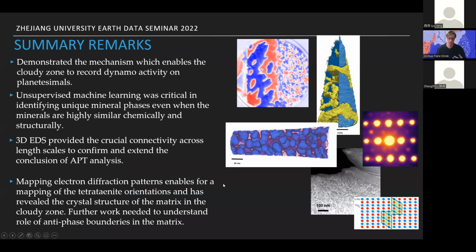The summary I'd like to point out is that we demonstrate a mechanism which enables us to explain why we're able to read magnetic records in the cloudy zone. Unsupervised machine learning was very critical in identifying unique phases, even when the minerals are incredibly similar. When you're trying to find a very weak signal against a very strong background, machine learning allows us to start pulling those details out. Crucially, we used 3D EDS tomography to project connectivity across length scales and extend our conclusions from atom probe, all the way from the atomic up to the micron length. And finally, mapping in electron diffraction enabled us to look for tetrataenite orientations, and it gave us the actual structure of the cloudy zone.